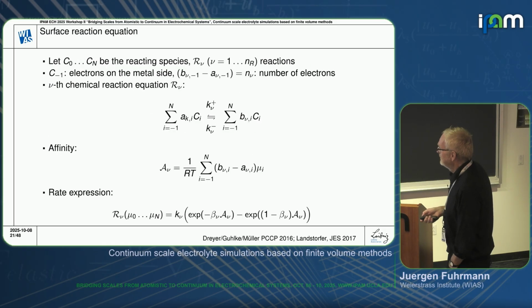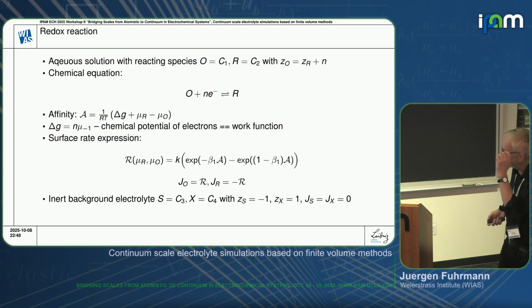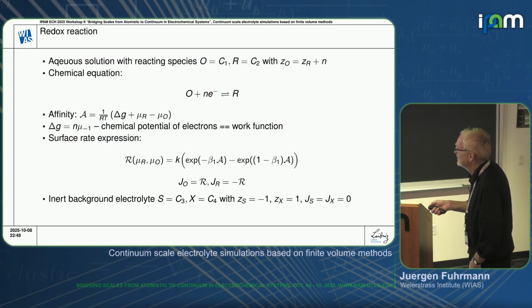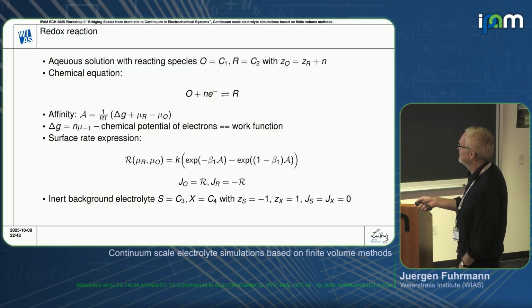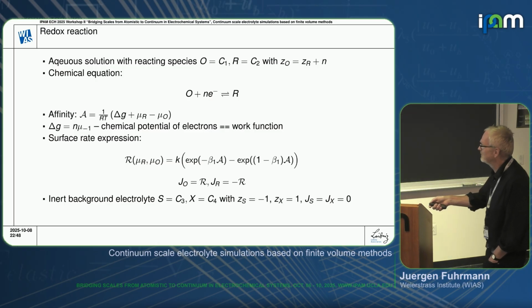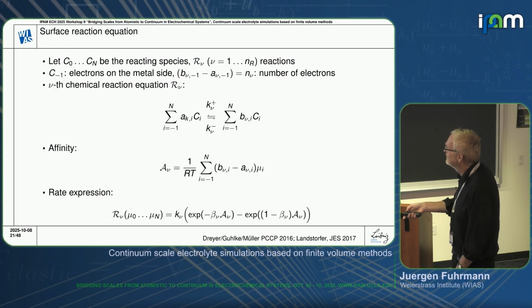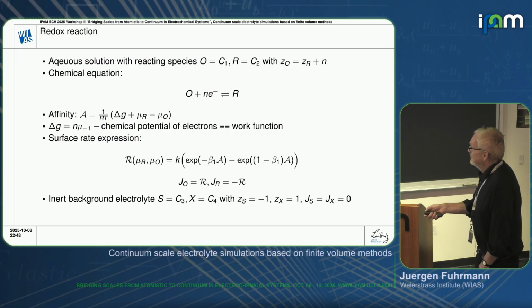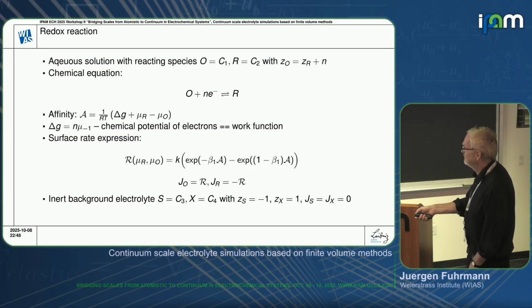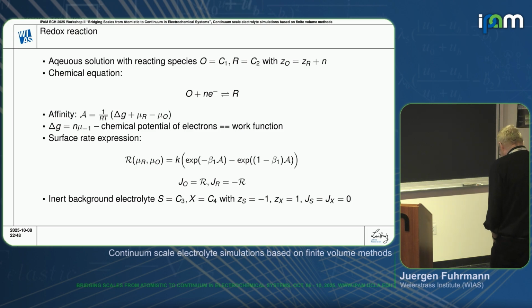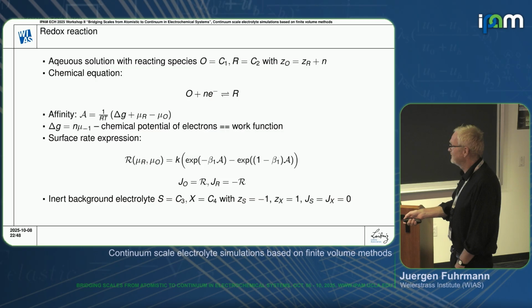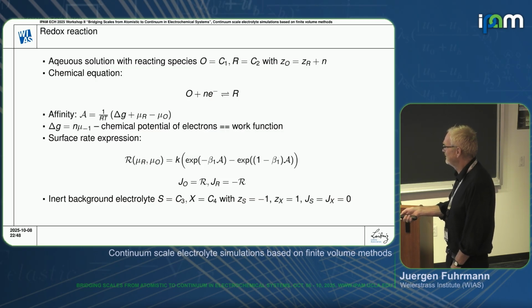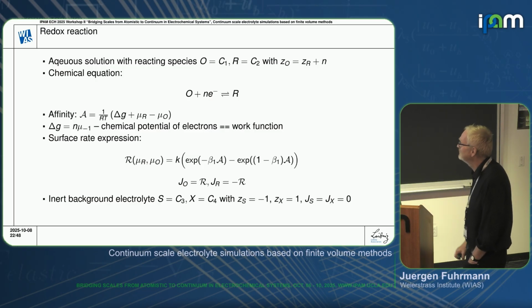And then we can just look at these expressions. For instance, if you assume we have just a simple redox reaction, where we have the species R and O with this kind of simple chemical reaction, then this would be our affinity. Here we would also introduce the chemical potential of the electrons or the work functions as a parameter in this affinity term. So they basically take part in our reaction system as species number -1. And then we get the surface rate expression. And this would be then the fluxes which occur in the boundary condition for our Nernst-Planck equations. And in addition, we can also introduce the inert background electrolyte, where we then have a species S and X, which are concentration numbers 3 and 4. And we can look at this at the scale of the